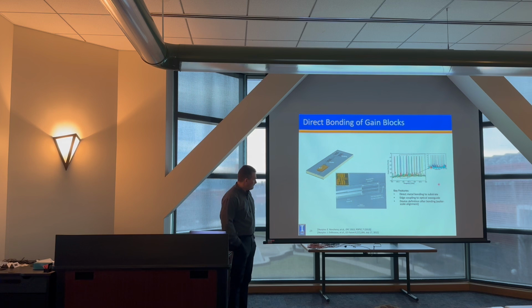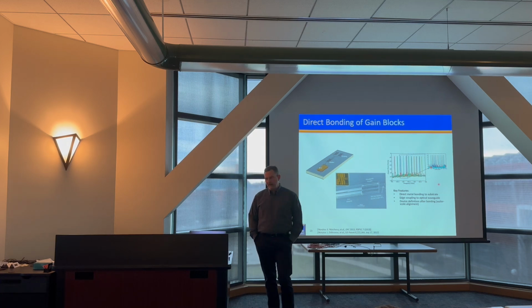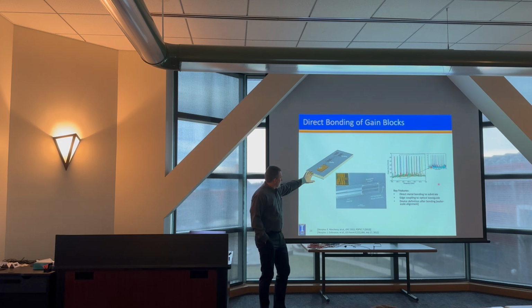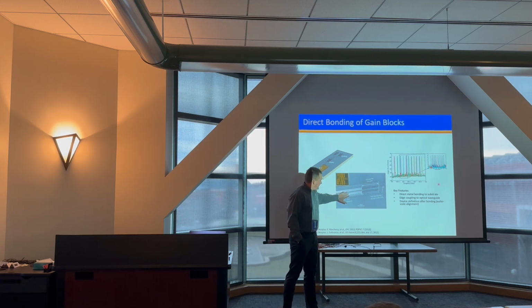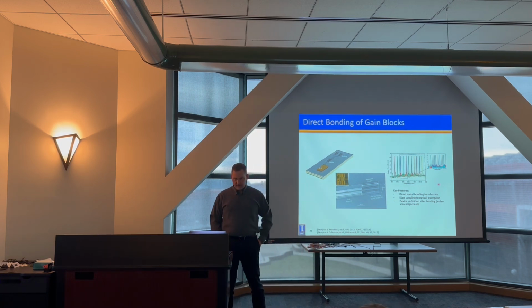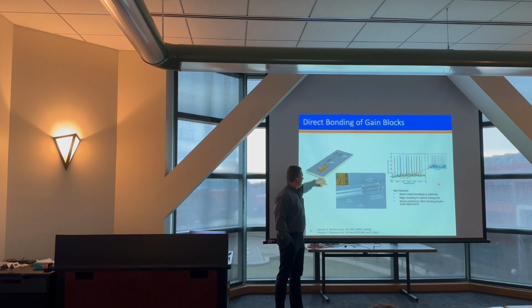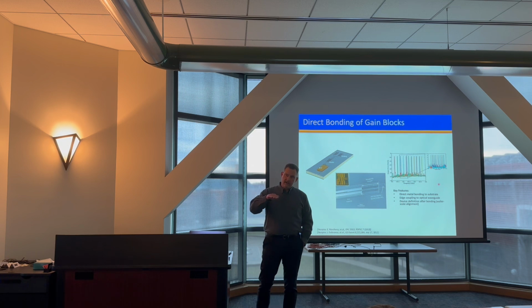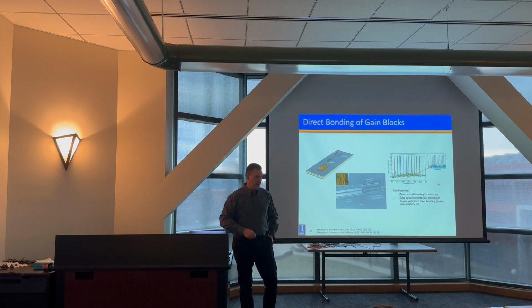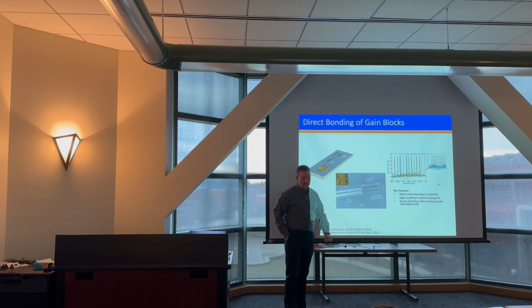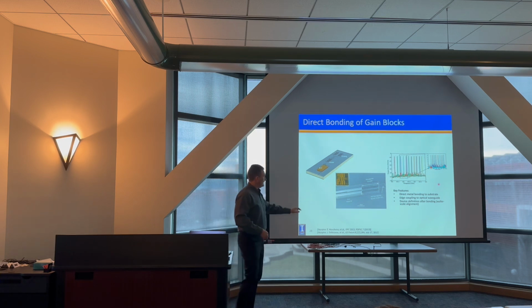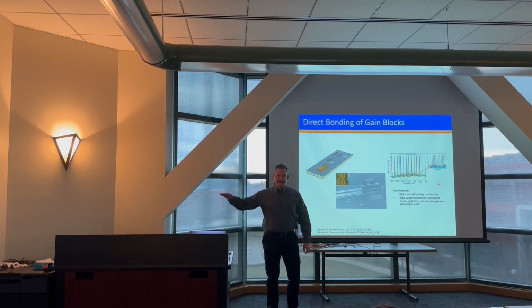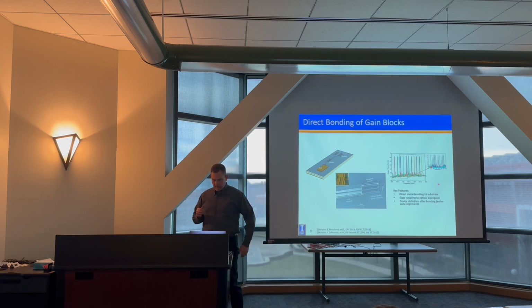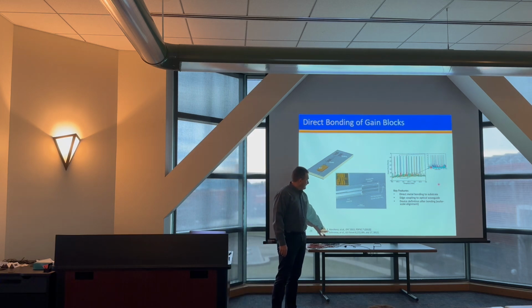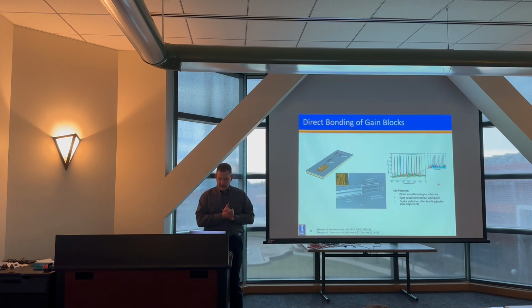And then prior to coming to Illinois, I was involved with a group that was doing direct bonding of III-V material to the silicon, creating basically bridge waveguides between the gain media and the silicon waveguides, so that you were able to make tunable lasers using an integrated gain material, where now instead of coupling across an interface, it's edge coupling. So there's still a little bit of optical loss here and a little bit of optical loss there associated with bridging between the III-V and the silicon, but it's not going the entire length of the device. So the loss is lower. And that was the basis for a company that's still out there making silicon photonic devices.